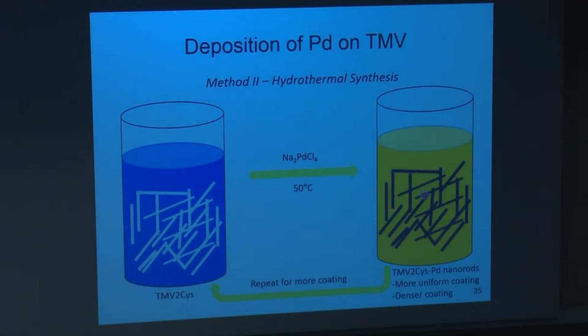So one of my former students, Lim, noticed that the palladium would reduce on the surface of silica particles when the particles were heated at 50 degrees. These were silica particles that were functionalized with either amine, thiol, or carboxylate groups. And so he decided to try the technique with just TMV and palladium, and just heating the solution to a high temperature, in this case 50 degrees C, to see what happens.